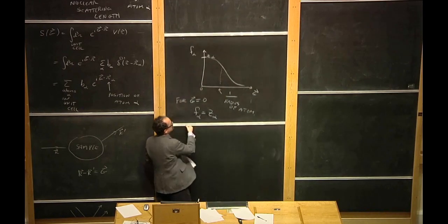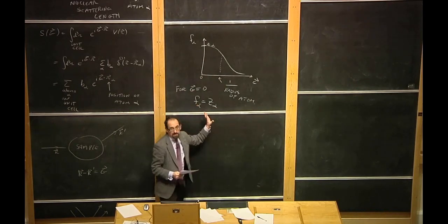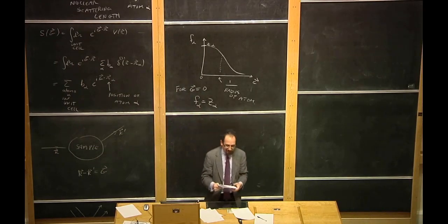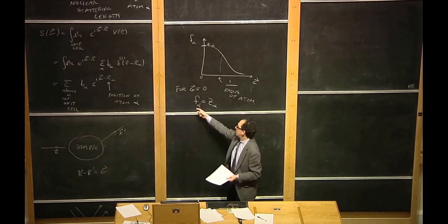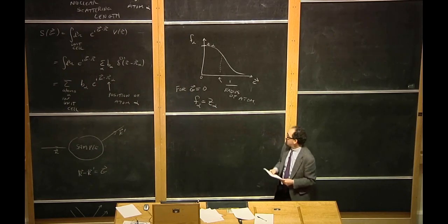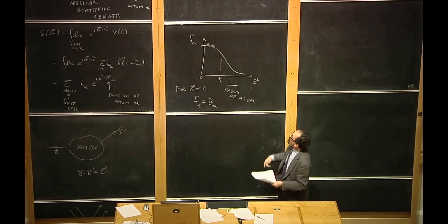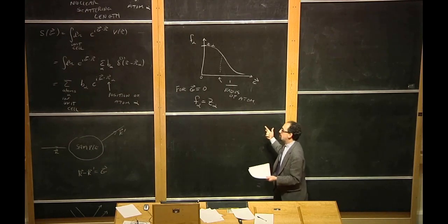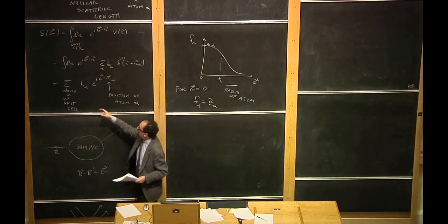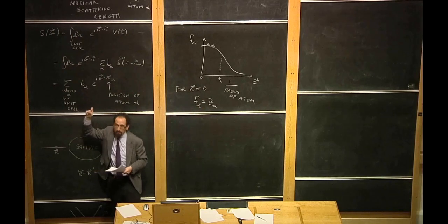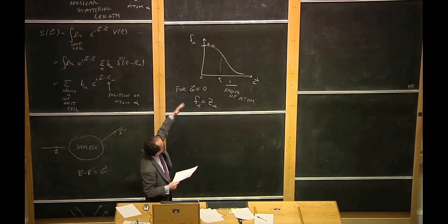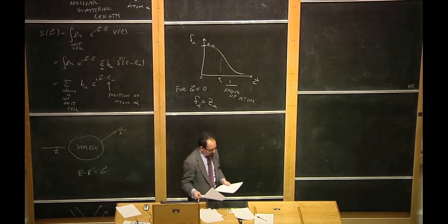Very frequently, people just make the approximation that f of alpha is a constant, and the constant is just the number of electrons, because if you have more electrons, you scatter more off of the atom. So let's assume that the form factor is independent of g and is basically just proportional to the number of electrons in the atom. It's not a horrible approximation. It isn't completely right, but it's not too bad, and it makes your life a lot simpler. It makes the X-ray problem look a lot more like the neutron problem, where this form factor, this b, doesn't depend on g anymore. It doesn't depend on the reciprocal lattice vector. But strictly speaking, f should decay as a function of g as well.